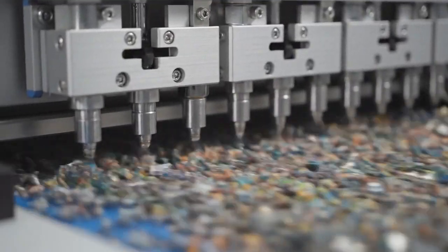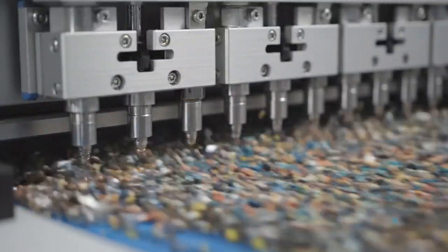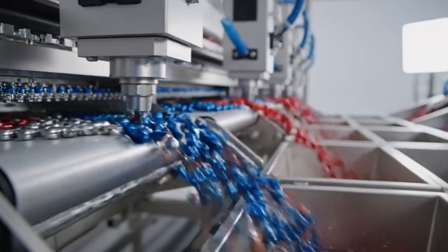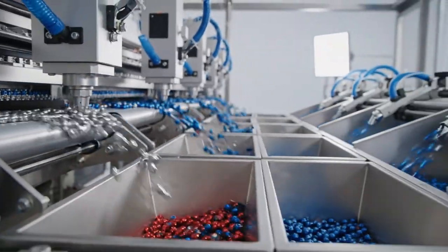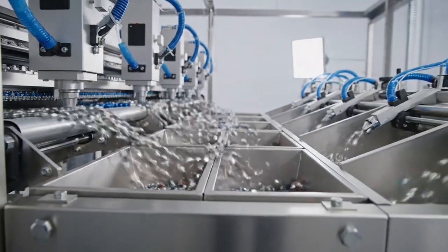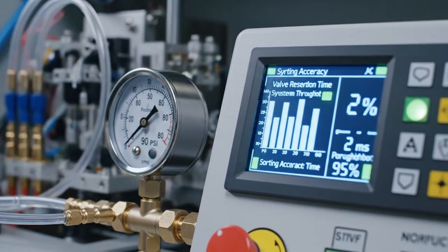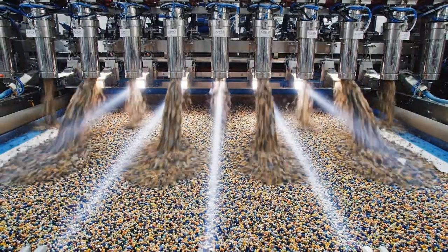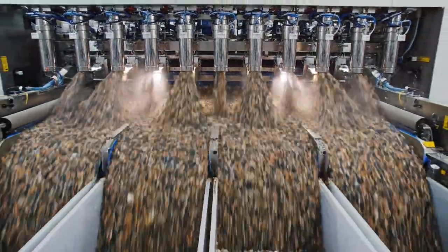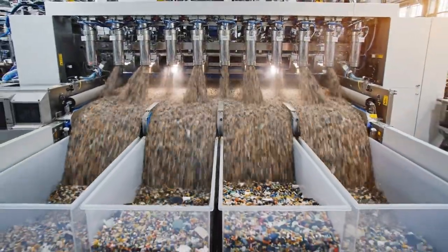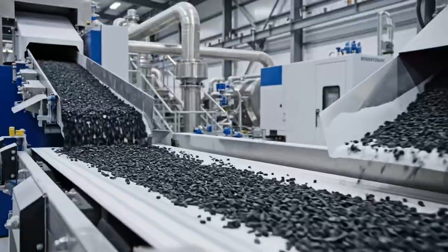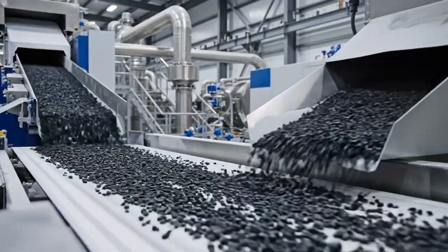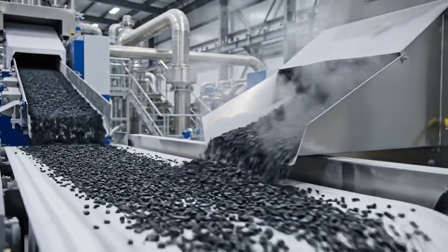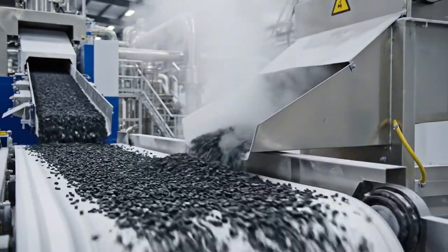When a particle is identified as belonging to a specific material category, compressed air jets positioned on 12-millimeter centers along the conveyor width fire with millisecond precision, ejecting the targeted particle into designated collection bins. The air pressure is 90 pounds per square inch, the valve response time is 2 milliseconds, and the sorting accuracy exceeds 95%. It is a ballet of pneumatics and photonics playing out thousands of times per minute in a cascade of decision-making that would paralyze human operators.